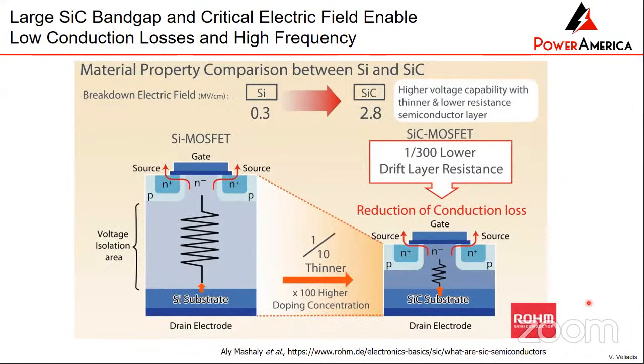Okay, so just to give you an idea, if you look at a silicon device, you can see it's very, very thick. And for the same voltage capability, the silicon carbide device becomes 10 times smaller. So 10 times smaller means electrons have a smaller path to cross. So that's lower conduction losses. And then when you're operating at high frequencies where you're switching the device very, very fast, because you have a smaller path here, it switches faster with lower switching losses. So that's the big advantage of silicon carbide and GaN power electronics.